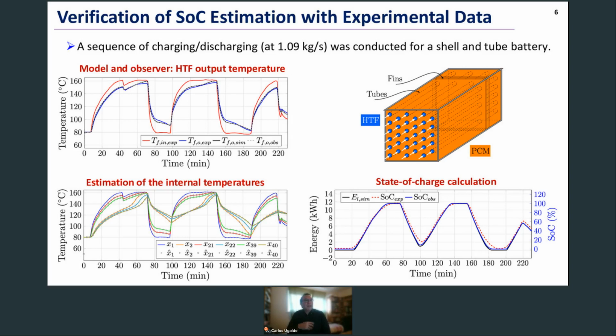To verify the state of charge estimation method, simulations have been conducted for which a real thermal store of a heating application was adopted. This is a shell and tube unit with the shell filled with a high-density polyethylene PCM. Inside the tubes, a synthetic organic heat transfer fluid circulates. The thermal battery was modeled using a discretization approach. The observer was designed using the model of the battery and the state of charge calculated as discussed in the previous slide. So a schematic is provided at the right-hand side for this thermal battery.